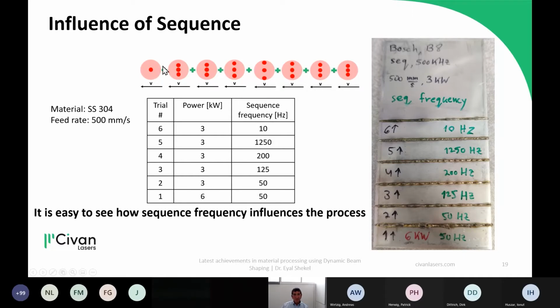So we created here a sequence. This is work that was done together with Bosch and IFSW. We created a sequence where we start with a single point, and then we go to 3 points, and the distance between the 3 points grows, becomes larger, and then becomes smaller again. So basically, we increase and decrease the whole beam size. This is done in a sequence that we pre-program in advance, and we change the sequence frequency, how fast it happens. And we did it with a feed rate of 500 millimeters per second.